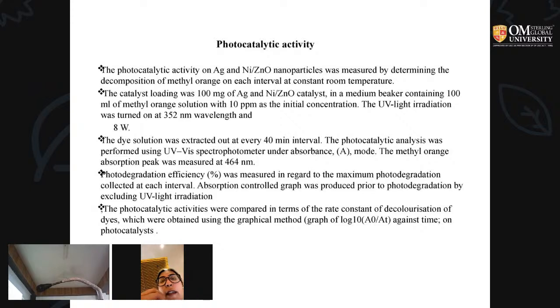In this study I am mainly comparing the photocatalytic activity of these transition metal compounds, silver- and nickel-doped nanoparticles. I have taken zinc oxide as a nanoparticle, doped with silver and nickel respectively, and measured the decomposition of methyl orange at each interval at constant room temperature. The catalyst loading was 100 milligrams of silver- and nickel-doped nanocatalyst in a medium beaker containing methyl orange solution with some initial concentration. Then UV visible light was applied at 352 nanometer wavelength and 8-watt power. The dye solution was extracted at every 40-minute interval.